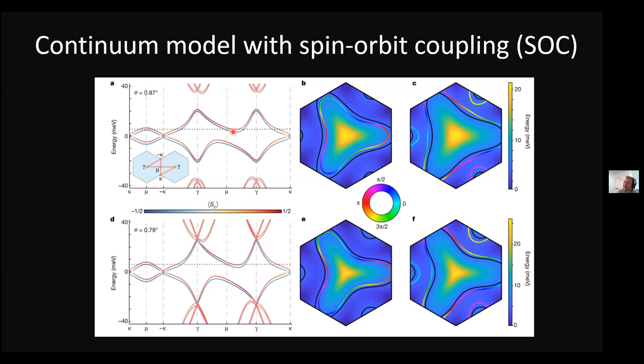But what can happen, and what we think may be happening and enhancing these correlations, is that in certain regions of the Brillouin zone you could have flatter regions and less flat regions, where you could have conditions for enhancing the interactions. So this is more of a speculation than what these graphs really suggest. But whatever the origin of superconductivity in this system, spin-orbit coupling alone, without interactions, cannot explain this blip in the Hall resistance. So you have to have some sort of interactions happening beyond that.